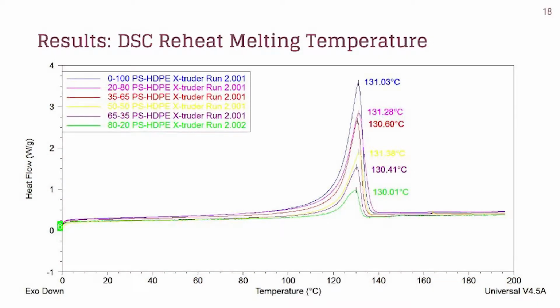The last graph that was produced was the reheating curve, and this also shows the melting temperature, which remained constant at around 130 degrees Celsius. This is useful for knowing that even as the polystyrene content increased, the melting temperature remained consistent throughout, showing that the mechanical properties were not compromised even with increasing temperature.